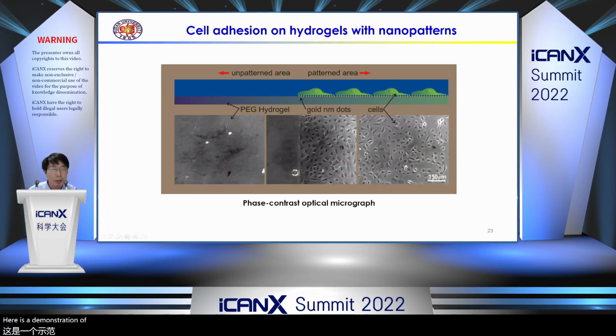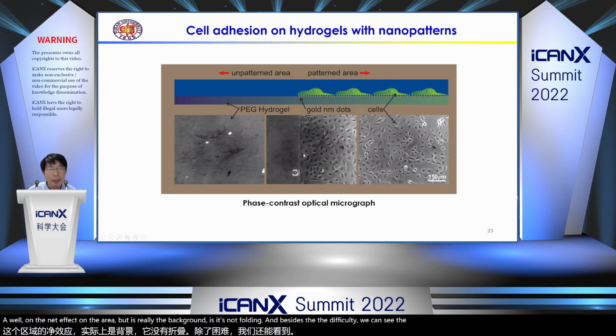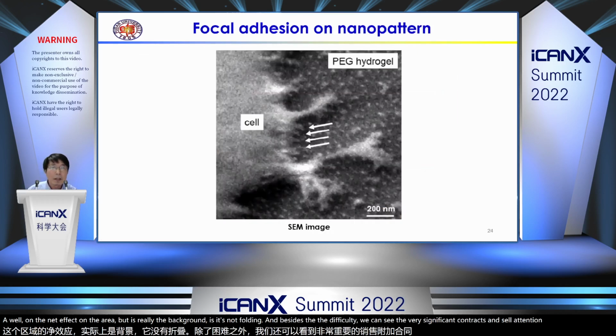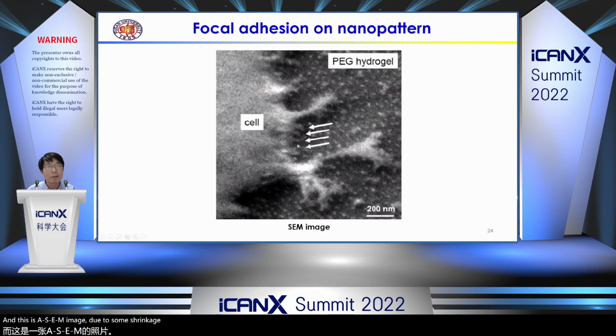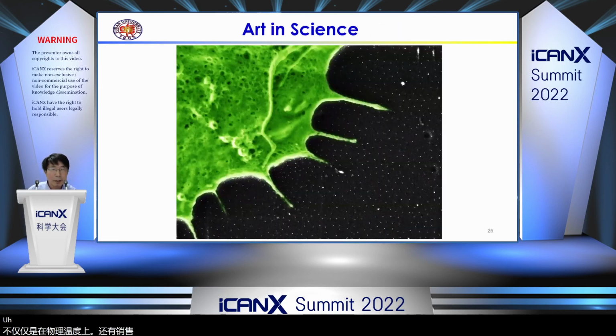Here is a demonstration of the cell culture. You can see cells can adhere well on the nanopatterned area, but the background is non-fouling. And beside the dip coating, you can see the very significant contrast of cell adhesion. This is an SEM image, with some shrinkage of the cell during the sample preparation. You can see the cell adhering to the nanodots. So our technique is successful, not only in the chemistry and the physics, but also in the cell experiment. One of my graduate students colored the cells and used his picture to join a competition for scientific art. So I always encourage my students to enjoy scientific life through art. So personally, I also like this image very much.